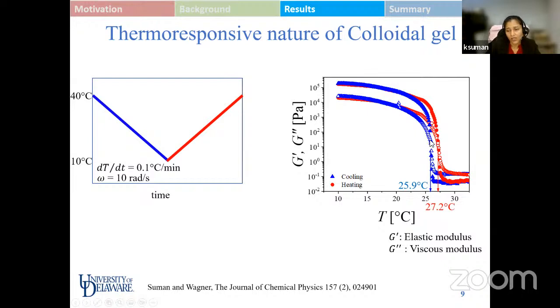And also, since in the cooling cycle it is coming from a liquid state, it's easier to transition into the soft solid state. Whereas when it is coming from a more constrained soft solid state, which is in the heating cycle, it takes a longer time to transition from a more constrained to a less constrained system, and therefore the transition shifts to higher temperature, which is why instead of 25.9 we see it at 27.2. So the initial state at which we are starting the transition matters a lot, because it is not following identical rearrangements during the transitions. So does that answer your question?